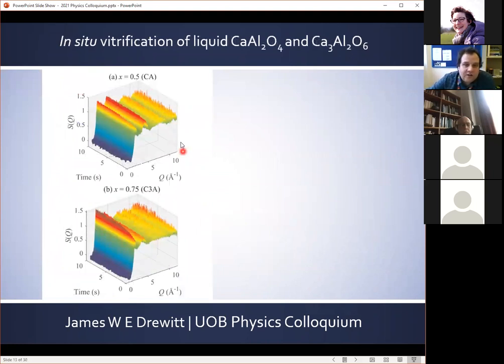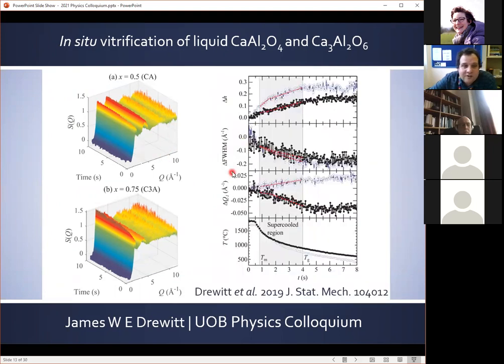Here I show a series of structure factor measurements for the CA, equimolar calcium aluminate liquid, and tricalcium aluminate liquid, as the liquid is supercooled from high temperature through its glass transition into the solid glassy state. The first thing we can observe is a clear evolution in the first peak, the so-called first sharp diffraction peak, on cooling from the high temperature liquid into the glass. If we look at this more closely, the top panel here shows the change in height of this peak, the change in its width, and changes in position over the supercooled region. This peak is highly indicative of changes occurring in the melt structure on a medium range length scale.